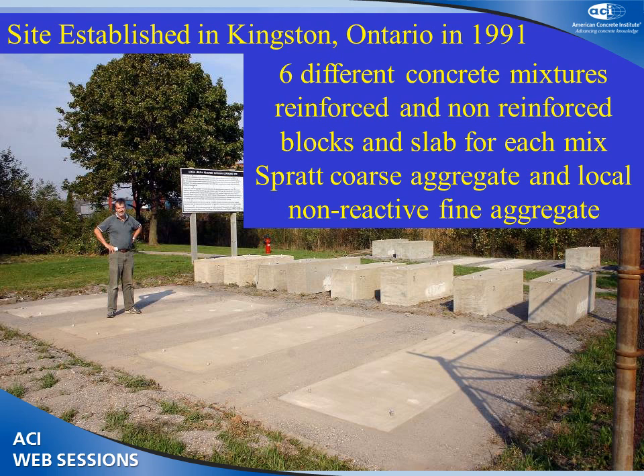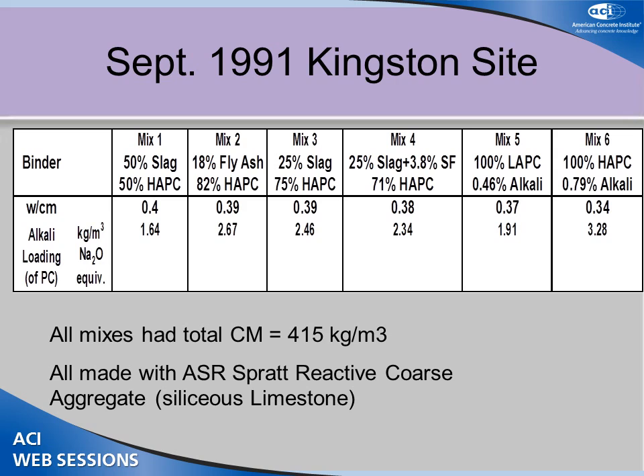We used 6 different concrete mixtures. It was placed at a Department of Transport site in Kingston, Ontario. We did sidewalk slabs, 4 of them showing there, and we did a series of large blocks. They're about 600 millimeters by 600 millimeters by about 6 feet long. There's the mixer units for you. And we did reinforced and unreinforced beams. The reinforced beams had about 1.4% steel area longitudinally, and we had DEMEC gauges buried in both the sidewalk slabs and in the beams.